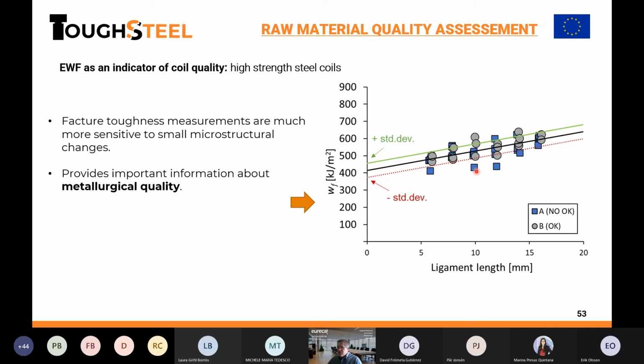But looking at the specimens that were showing strange behavior with the SEM, we detected that the inclusion content and the inclusion morphology were different. This is because the metallurgical quality is very sensitive to the toughness, or on the contrary, toughness is really related to the material cleanliness and the material microstructure. So small changes can really be captured, because fracture toughness measured by the essential work of fracture is a very local measurement. So small local changes can give big results. So we were able to discern this problem in the production of the steel.